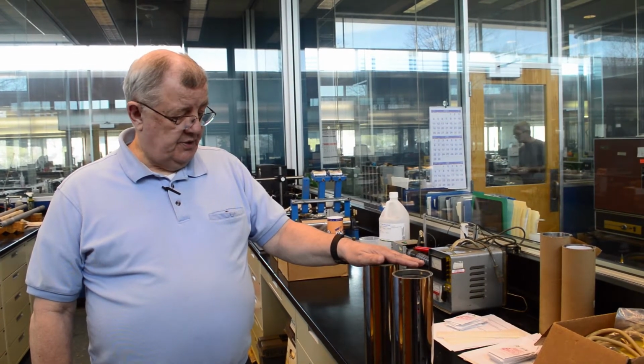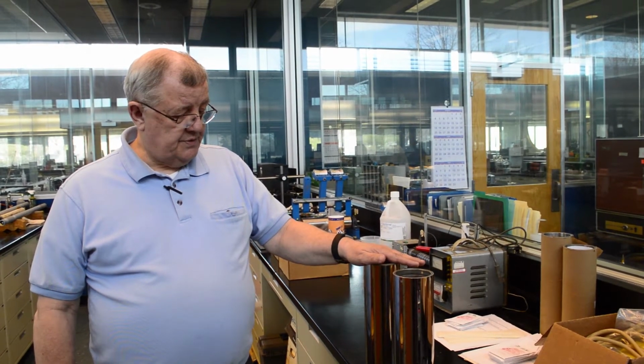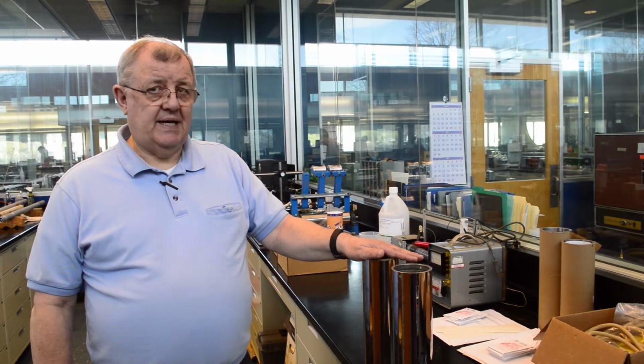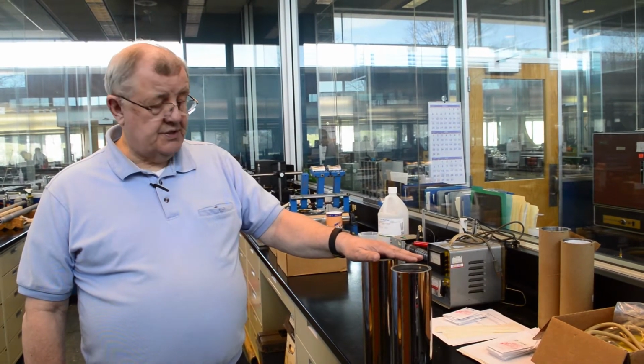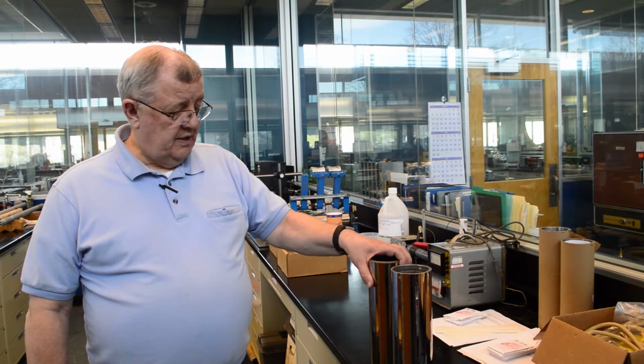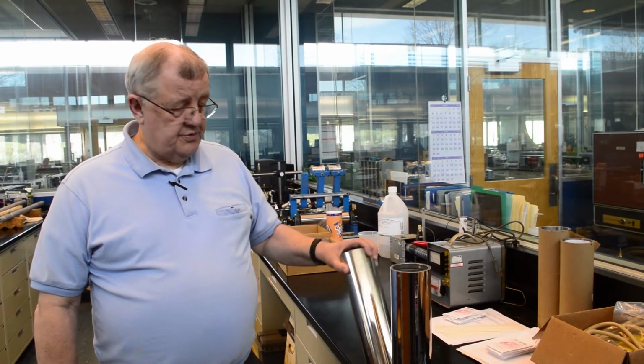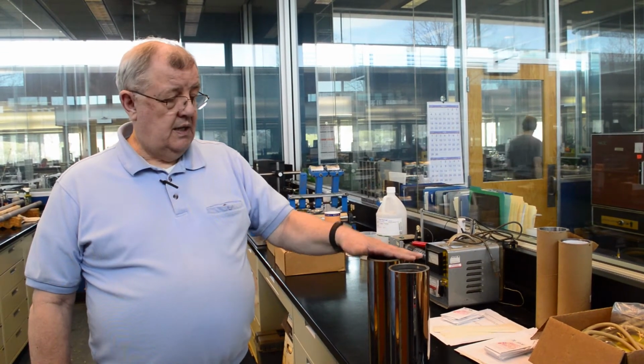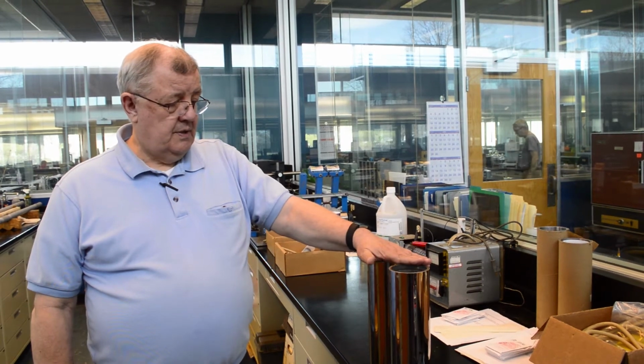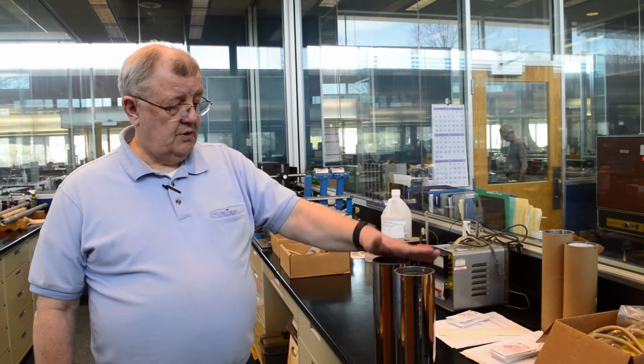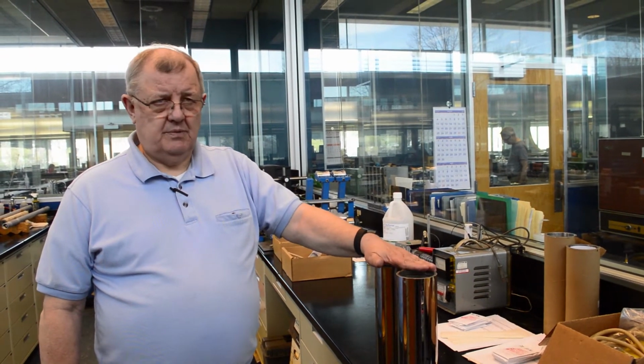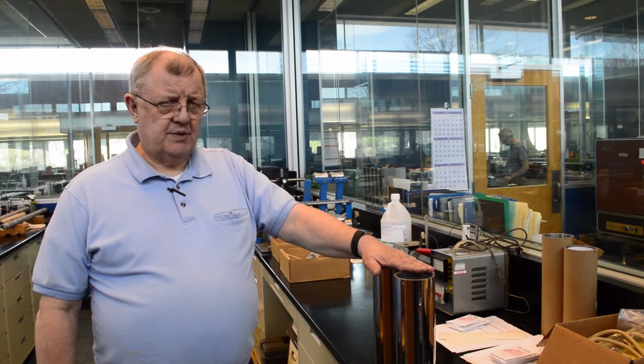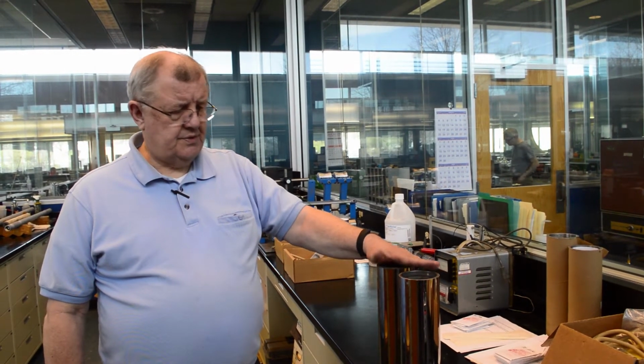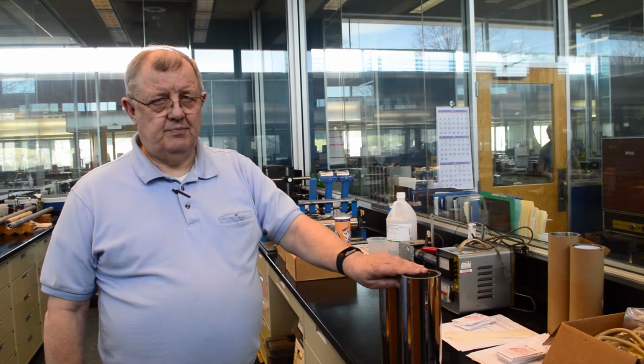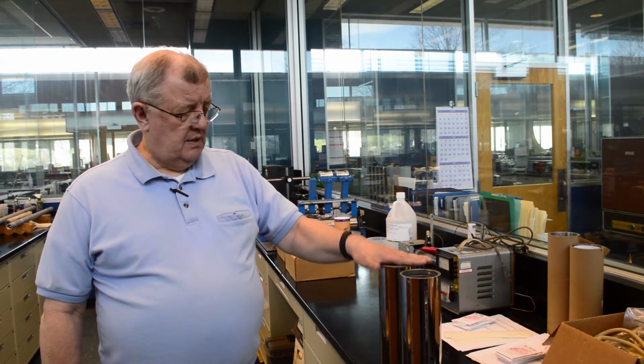But our new material, which we call Chrome Plus, is also a carbide, but it's not tungsten carbide, and it does have good thermal conductivity. It will not cause the end user to have to slow his line down. In terms of hardness, the coating is very similar to chrome. They're about 68 Rockwell C. Thickness, chrome thickness is typically 3 to 6 mils.